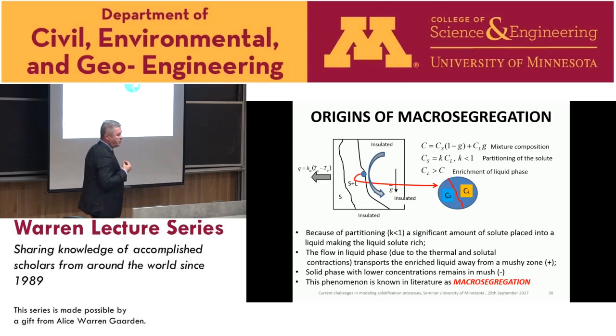What are the origins of macro-segregation? If you look at the system, let's say this is a cavity where we are extracting the heat from the left side, for instance, and everything else is insulated. Then we have a formation of solid, and then a mushy region, which can be quite wide, and then a liquid phase. If you look deep into the mushy region, you can see this partitioning. When solidification starts, the solid which is formed is poor in solute. And that solute has to go somewhere. It stays in the liquid.